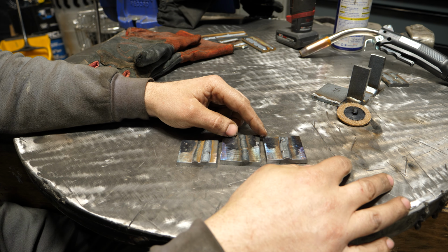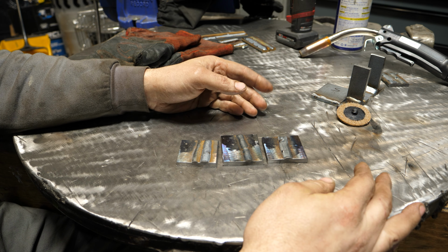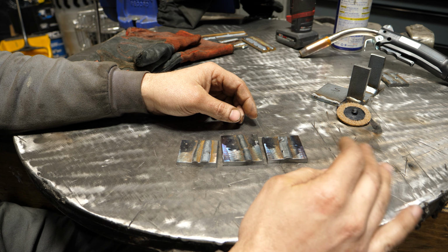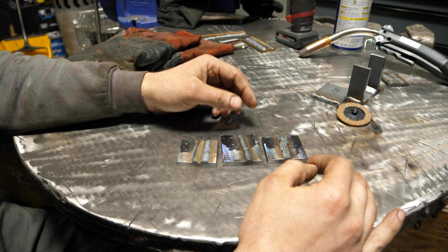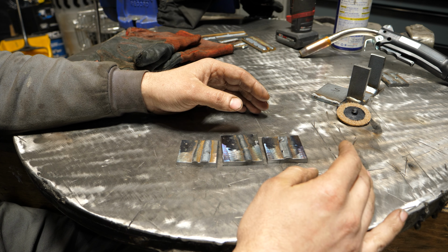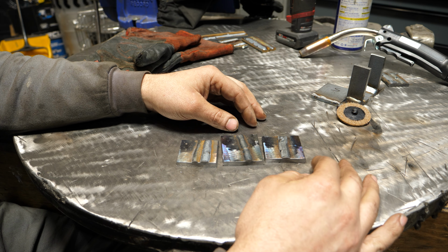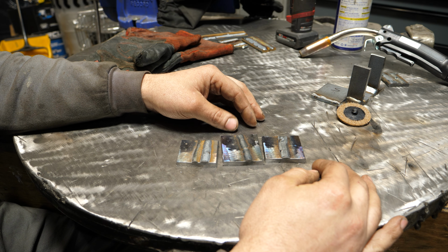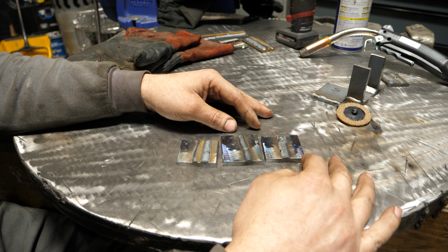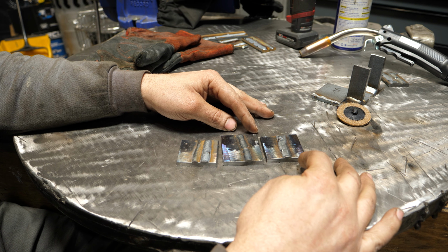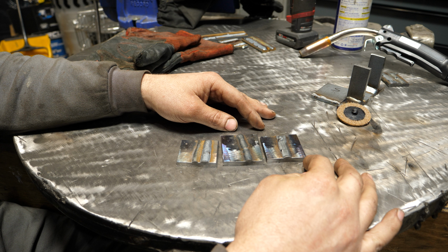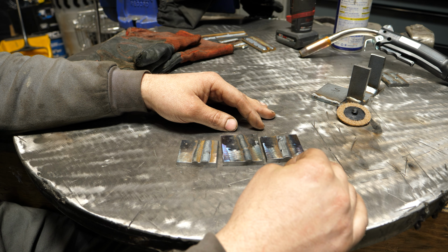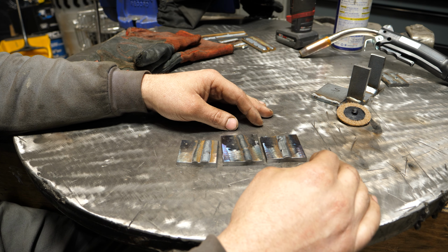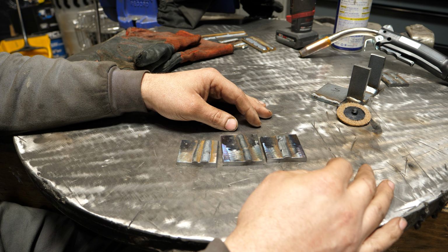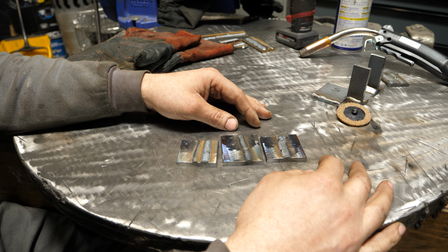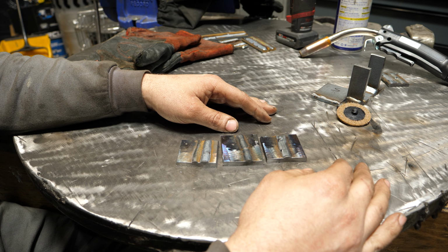The cut and etch gave some pretty interesting results, and one of the things you guys got to remember is that short arc MIG at its hottest and highest settings is essentially the penetration you're going to find at the lowest settings with spray arc, and different gas mixtures will also lead to different performance. So it's pretty apparent why spray arc is used, especially on thicker plates. It provides reliable deep penetration that you may or may not get with short arc, and that is highly desirable because the last thing you want is some poor welds with absolutely no root fusion, let alone penetration, on something that actually needs it. Failure is the name of the game in that case.